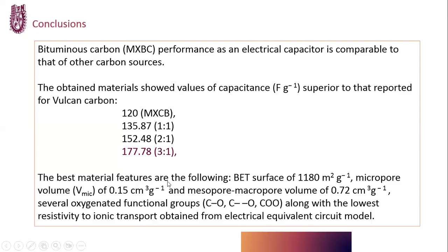The best material's features are the following: BET surface area of 1,180 square meters per gram, micropore volume of 0.15 cubic centimeters per gram, and mesopore and macropore volume of 0.72 cubic centimeters per gram, several oxygenated functional groups, along with the lowest resistivity to ionic transport obtained from the electrical equivalent circuit model.